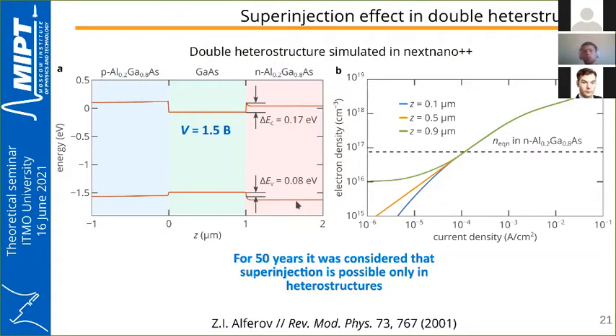I took a double heterostructure diode with gallium arsenide and aluminum gallium arsenide and performed simulations showing that the electron density in different points of the gallium arsenide can be 1-2 orders of magnitude higher than the equilibrium density in the aluminum gallium arsenide.